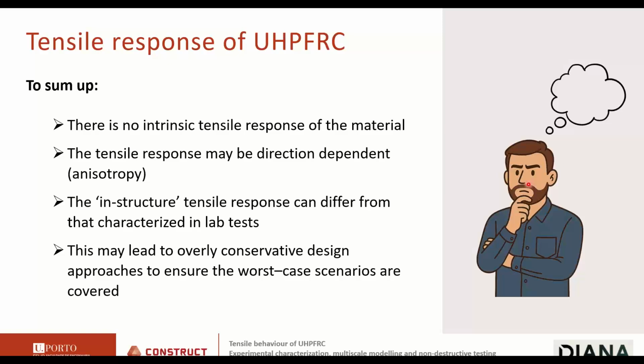So to sum up, there's no intrinsic tensile response to this material. It depends on how you cast, on the factors that I've described in the previous slide. So the tensile response may be direction dependent, as could be shown in the tests before. The tensile response of the material in the structure can be different from that obtained in laboratory tests. And typically, this leads to overly conservative design approaches because the designers need to cover worst-case scenarios.